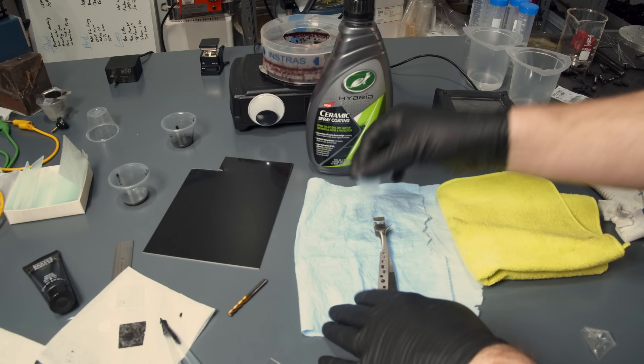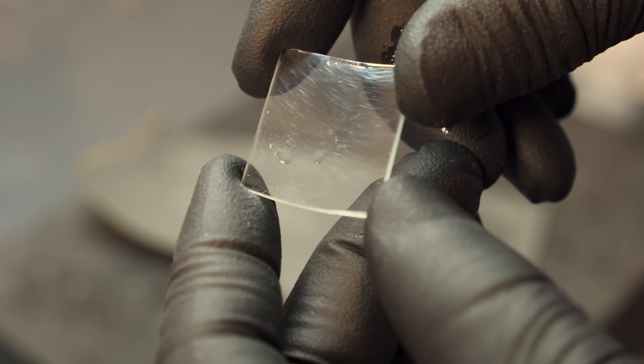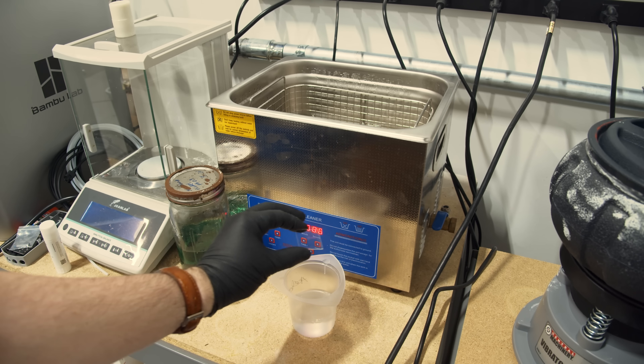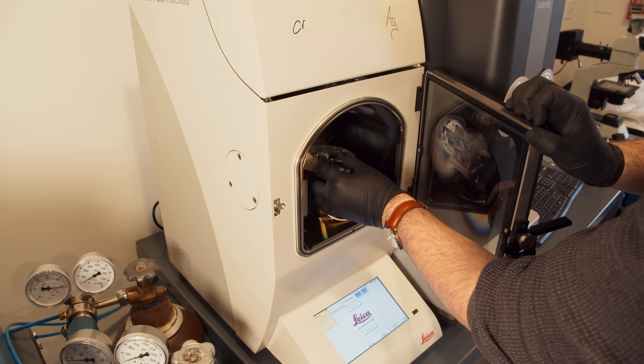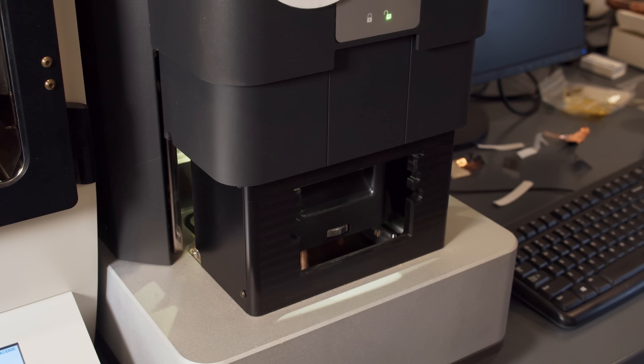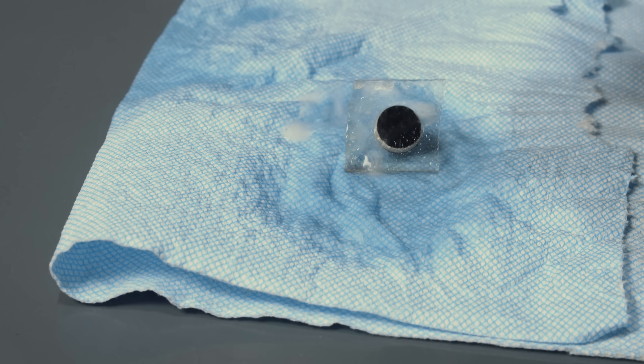So we're going to take a glass slide and scuff it up with 1500 grit wet/dry sandpaper to simulate the swirl marks you'd get on a real-life piece of glass. After scuffing it up, we'll clean it in the ultrasonic very carefully to remove all abrasive grit and scratched-up glass particles, avoiding false positives. Then we'll give it a quick sputter coat — about 10 nanometers of silver — pop it under the SEM, and take characteristic photos of what it looks like after scratching but before coating, to account for the abrasion process.